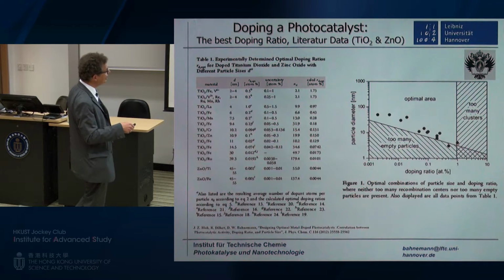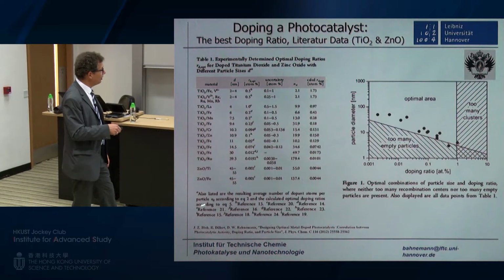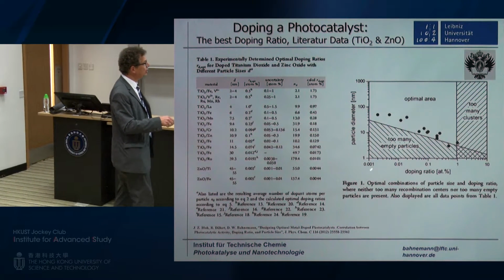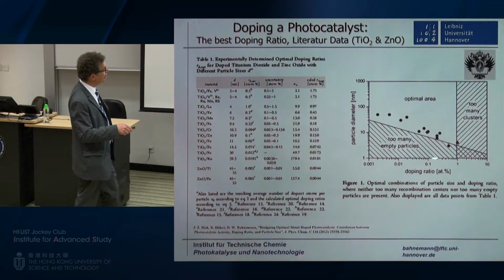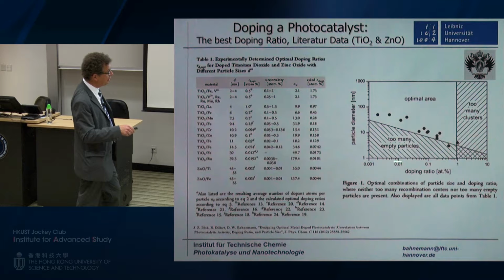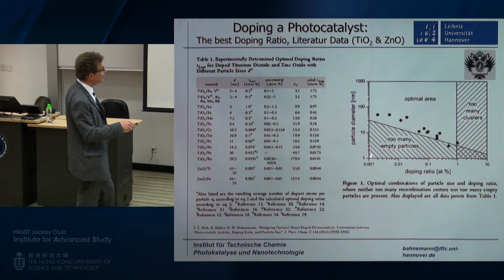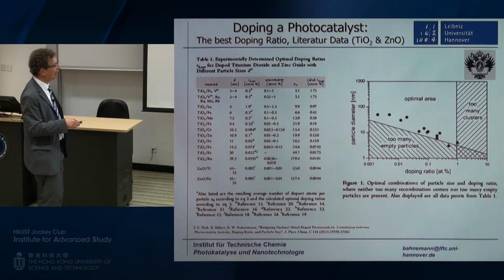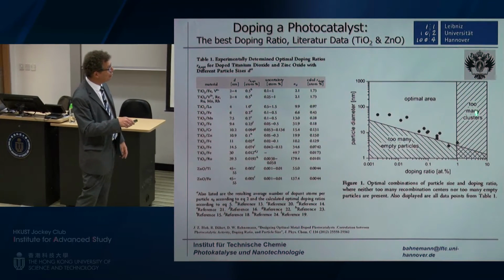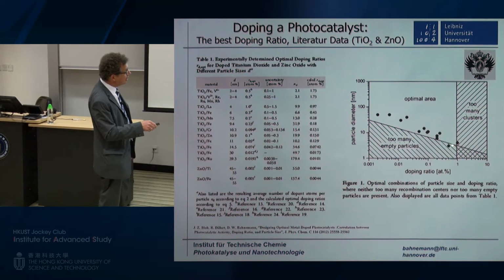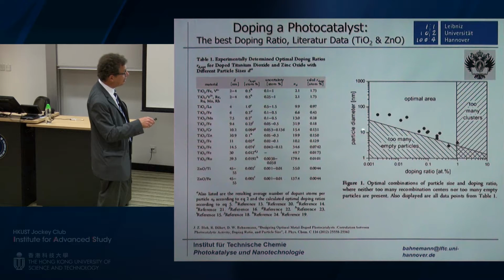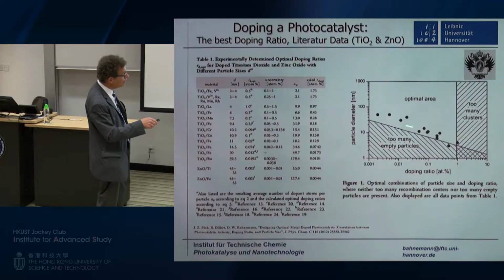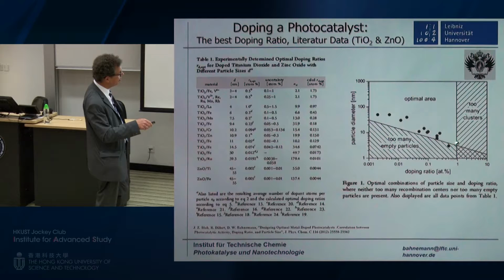We got all these data and our own zinc oxide data, and then we just now changed the plot a little bit by again plotting here the doping ratio on the x-axis, and on the y-axis now the particle diameter. You see the optimal area according to our model would be the ones above the area of the empty particles, not doped, and above and below the area of the clusters where you have recombination centers. And these are now the data points from the literature, and they are all in this optimal area. These are actually our data points here from the zinc oxide.